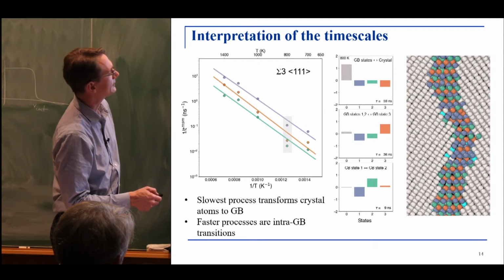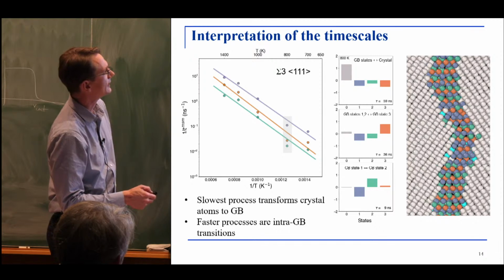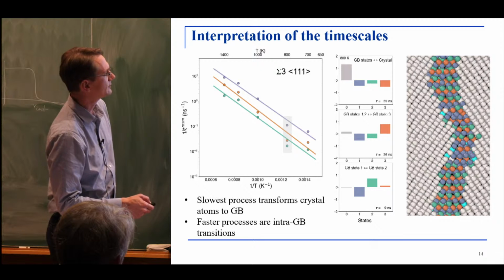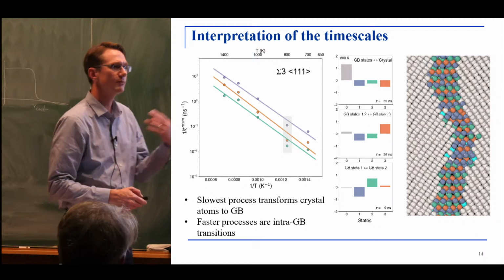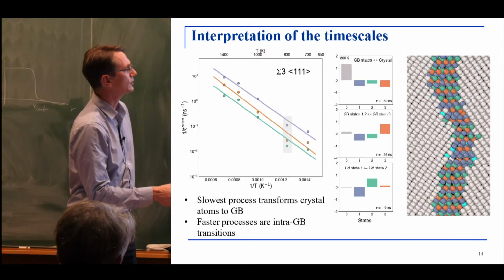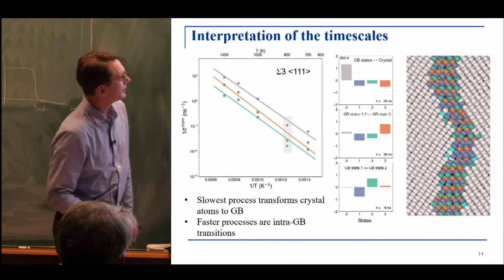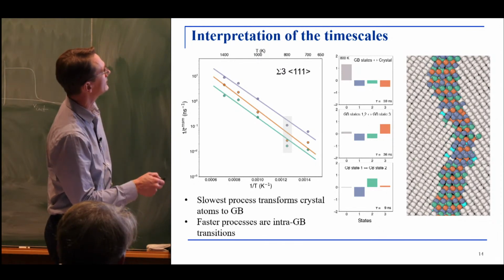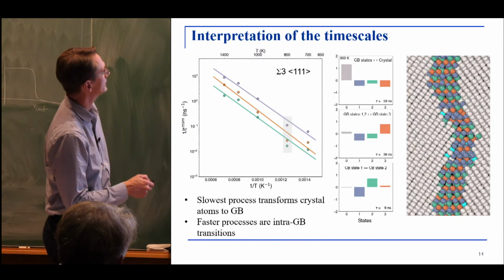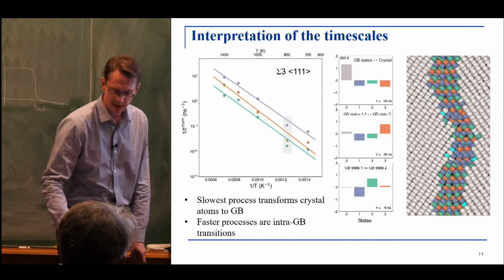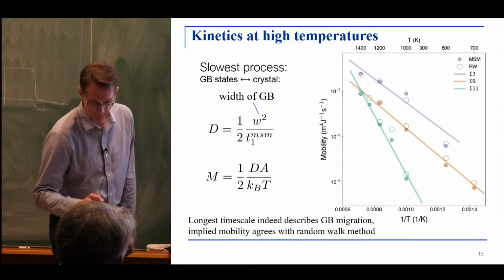For instance, you can see that the next one is a transition between states 2 and 3, between states 1 and 2 into state 3. And then the fastest one is between state 1 and 2. So you gain information about relaxations that occur inside the boundary. And if you plot these 3 timescales, we see that they are more or less following an Arrhenius law, which is probably to be expected for this kind of system.